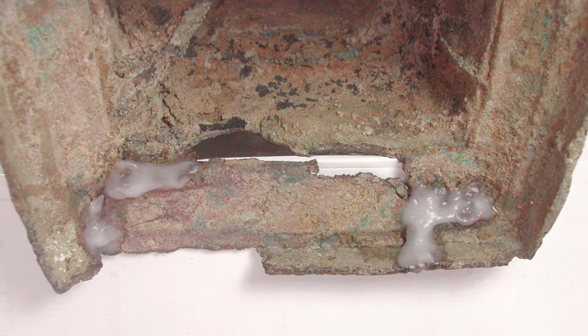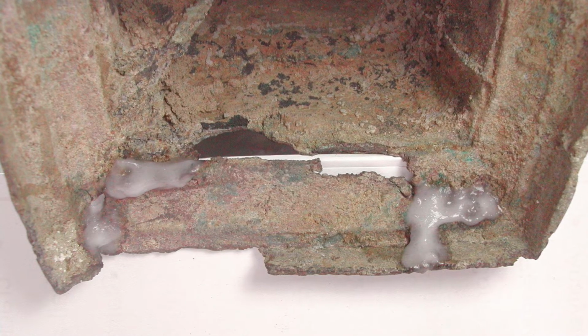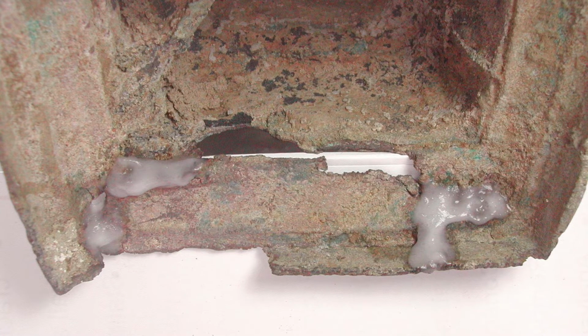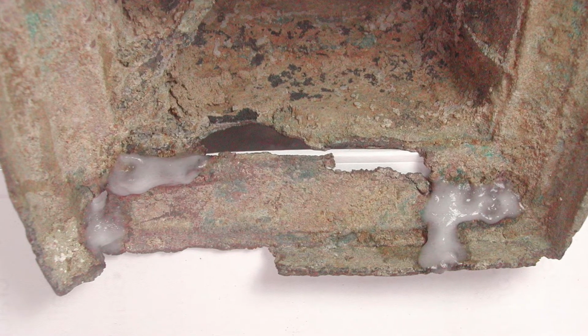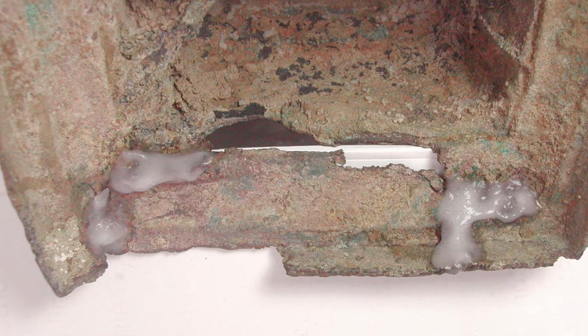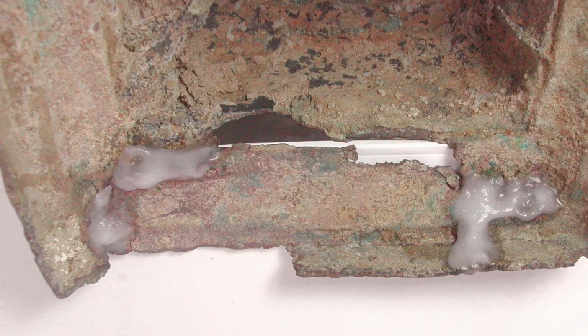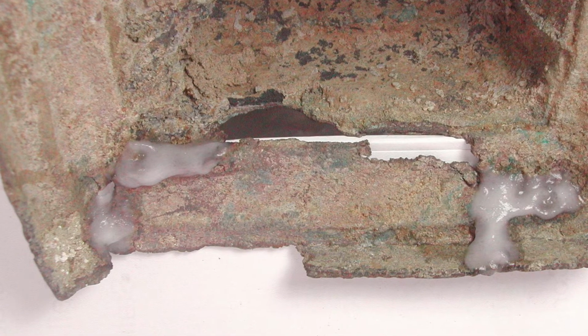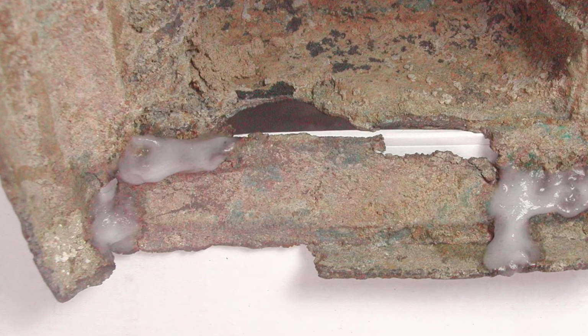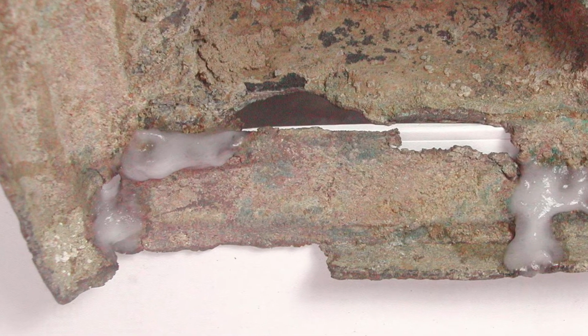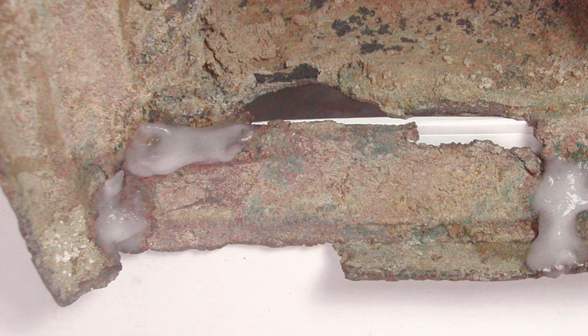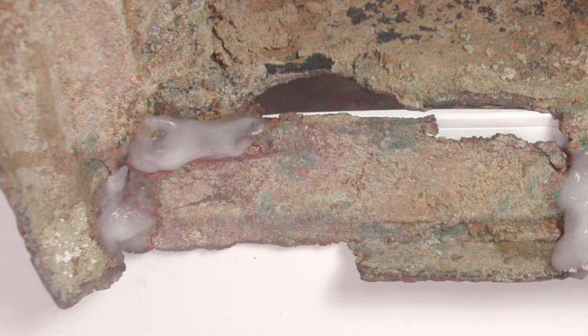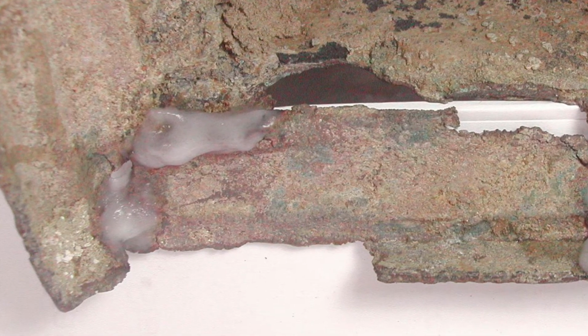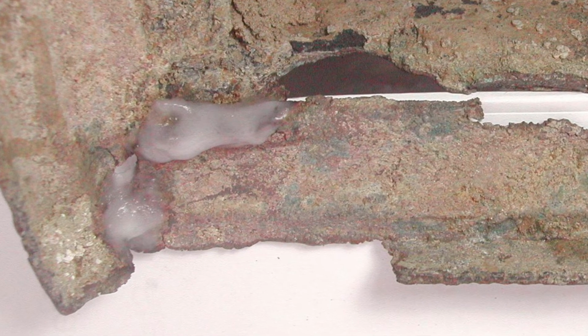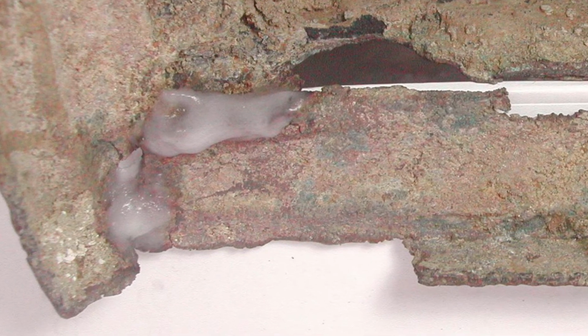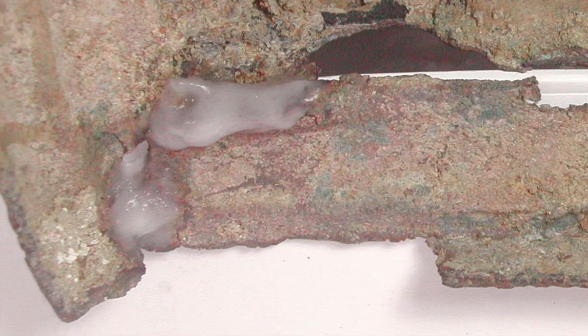Due to the misalignment of the bronze fragments in the front, the unsatisfactory old restoration had to be reversed. The goal was to do as little or no damage to the original substance of the antique bronze cast. It was decided to soften the synthetic polymer with a mixture of solvents and a bulking agent. This was chosen since testing showed that it would not damage the existing noble patina. To minimize any risk to the outer patina, the poultice was only applied to the inside of the sculpture along the old restored fractures.